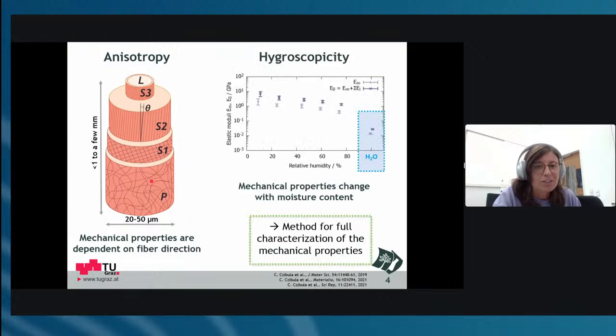And another thing that has always been a bit of a focus is hygroscopicity. I like this word a lot, but it's basically that the mechanical properties also change with moisture content in the fibers. Especially when you measure the fiber in water, you have a completely different material system at hand. And when you do it with contact-based methods, for example indentation, you just go in there like it's butter.